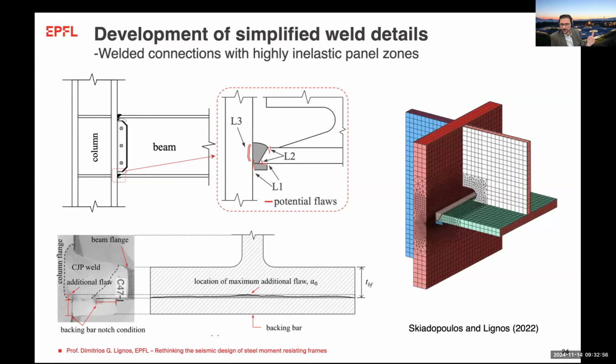So what we've done here is that, again, we used simulation-based design where we could explore the possibility of not removing the backing bar after the weld is completed, to minimize two things. Inspection processes, because if you remove it, then you have to inspect and make sure that the flaws are sufficiently small. Otherwise, you have to back gouge and repair. And obviously, we wanted to have a better quality also in this region so that we minimize the fracture potential, particularly in the case that we increase the energy dissipation in the panel zone.